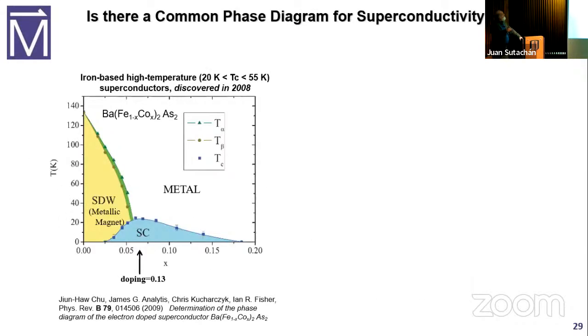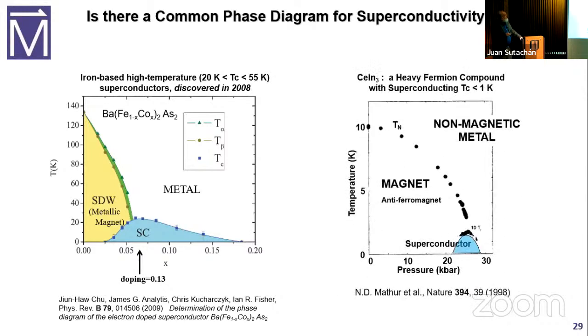But there are other families now. These don't have copper, they have iron, and they superconduct up to about 55 Kelvin rather than 125 Kelvin. And these have a real magnetic phase transition. So this is a type of magnet called a spin density wave. And over here, it's a non-magnetic metal. And where this phase transition is crashing down, instead there's a superconducting dome. It kind of looks like the cuprates, but it looks exactly like a material that's completely different.